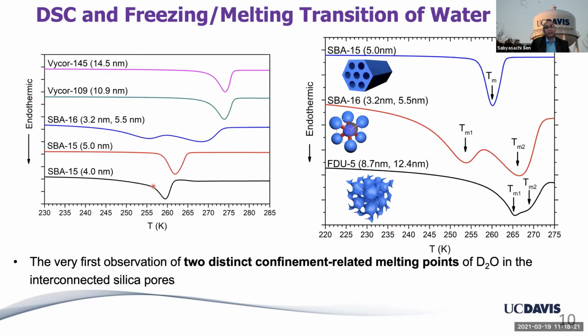Nanometer size creates a depression in melting point, and this is nothing not known before. This is a very well-studied phenomenon of depression of melting point in nanospaces following the Gibbs-Thomson law. That's what you would predict. These are some examples of the materials and the corresponding scans. What is new, though, is this is the first time we saw that if you have two pores, albeit interconnected, you can see two different melting points of water.